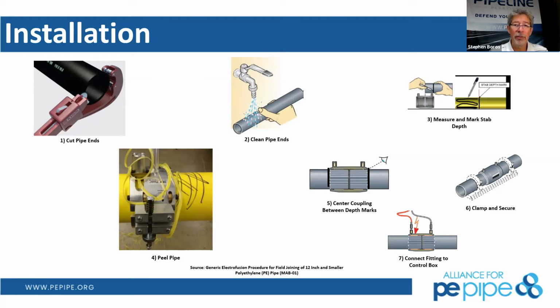But there are some processes if you're going to use clamps, rerounding clamps, to secure it and keep it in alignment on smaller diameter and even larger diameter. You want to make sure that pipe's nice and round with different clamping devices and rerounding devices to make sure you get a good joint all the way around, a good coupling.